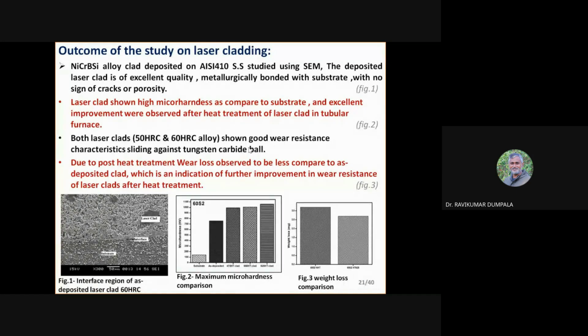Compared to the substrate, because the substrate's properties are always very low, by adding cladding your hardness increases so much. That is one step, a very basic process we are doing. Then further heat treatment is carried out, so properties are a little bit increased. Though we call it a duplex process, people don't call it that much, because the property variation is very small. You see that it is 800 to 950, something like that. There is a marginal variation in the microhardness,